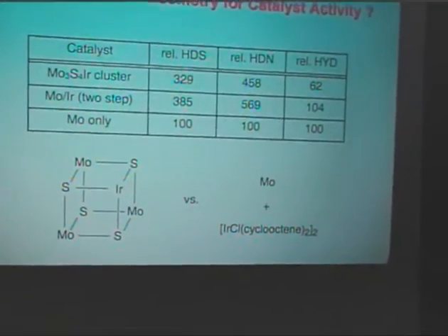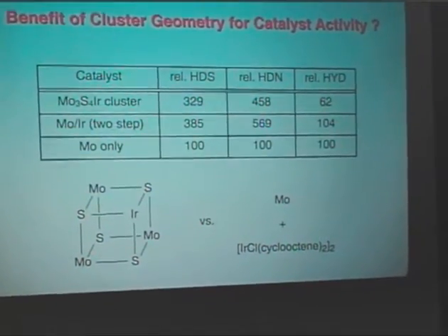The reason for that might be that we have a lot of carbon ligands on the molybdenum and also on the iridium, which will not fully decompose and cause deactivation phenomena in comparison to this two-step impregnated system. So we decided to go on with more experiments with just these conventionally prepared two-step impregnated systems.